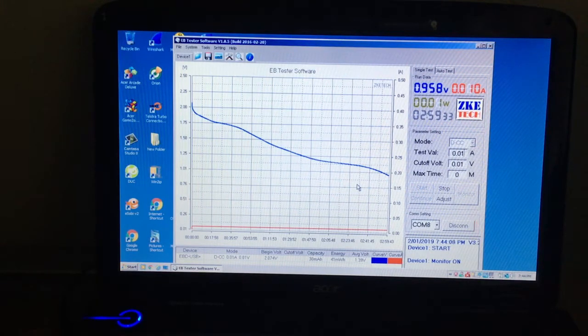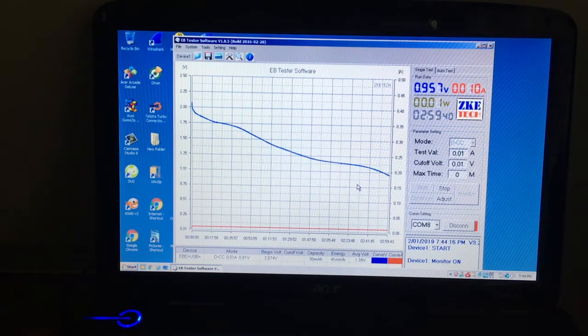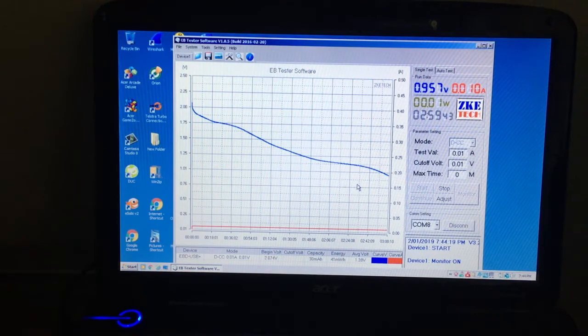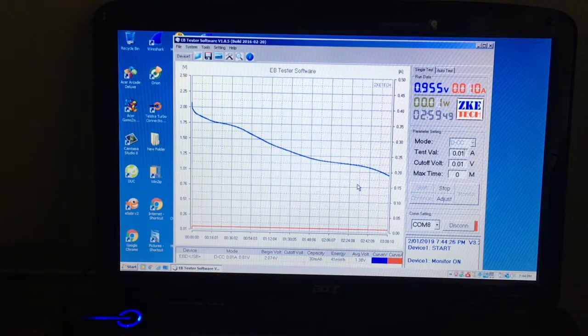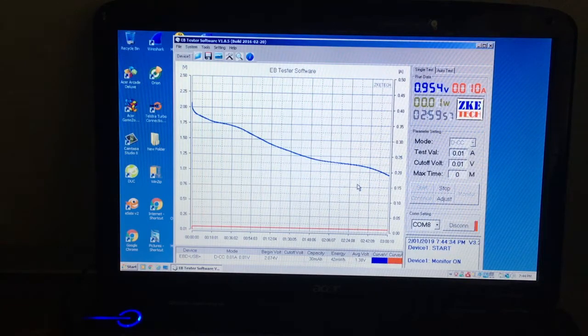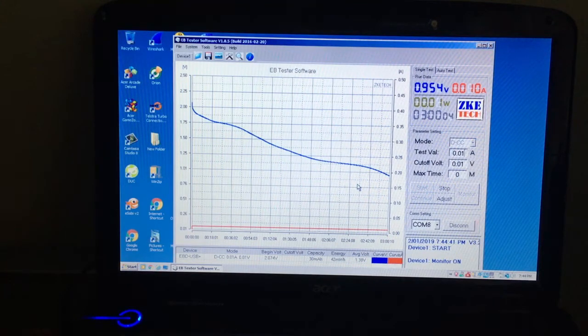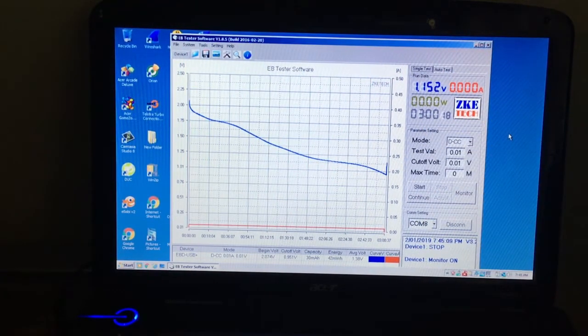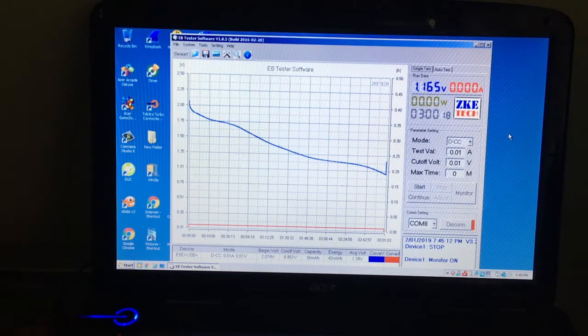That should tell us anyway if the cell's going to charge up and discharge and hold the same capacity. Sorry about that, but I just have to go. So it's not too bad to run. When you see the coating are actually made on the cell, it's not very pretty. Sort of dried out too much. It was 39 degrees today. So the cellulose acetate evaporated a bit too quick before I could get it sort of level on the cell. So it's sort of missing. And it's not that coated that well. I was surprised it was actually going to run this long. Till the next charge for this cell. Just turned it off. And voltage bounce back is 1.1 already and climbing. So it's still got some charge in it.